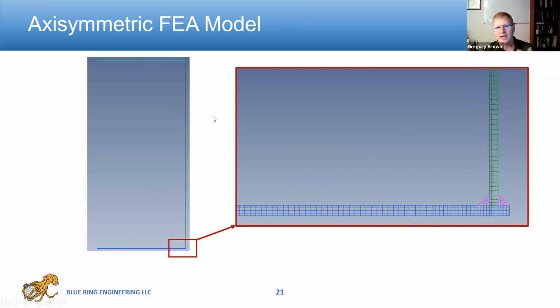We put product in the tank to put all the loads on the floor, the hydrostatic stress on the outside. The tank shell is in green, and then you have this floor to shell weld called the chime weld in the model as well. This location is usually the most critical location for storage tanks. What an axisymmetric finite element model is, you're actually capturing the full three-dimensional stress state, but you're just modeling a single slice of the structure, and you're assuming it doesn't vary around. It's just a more computationally efficient way to do things.